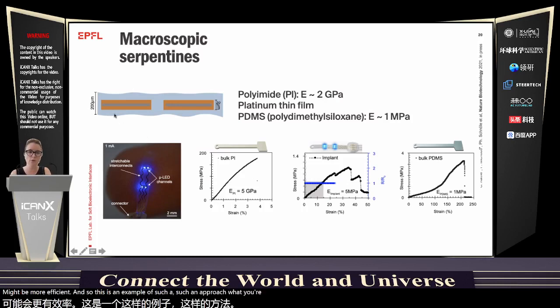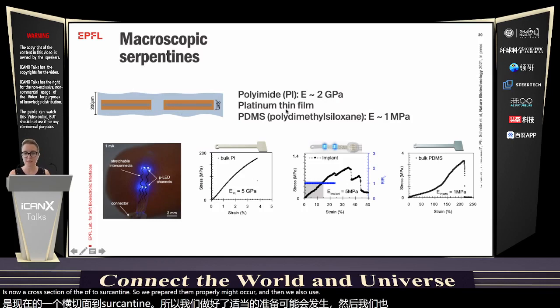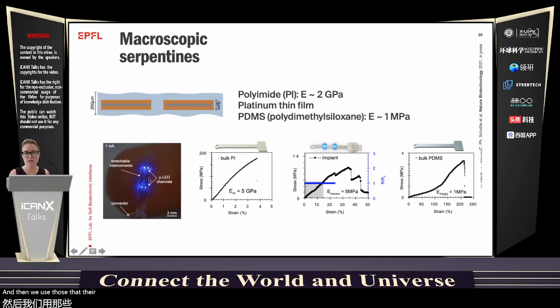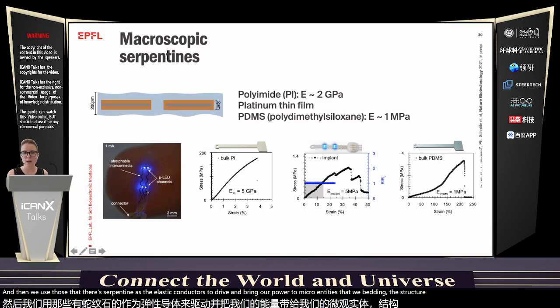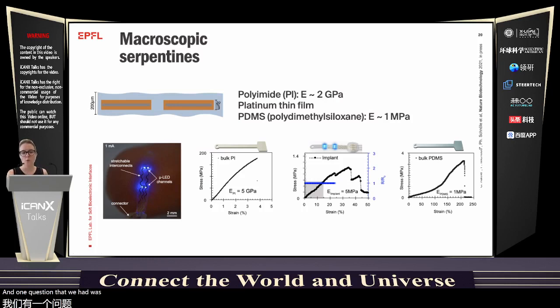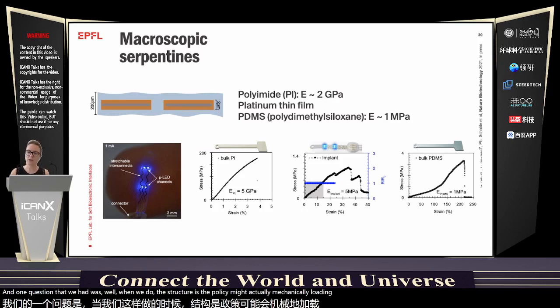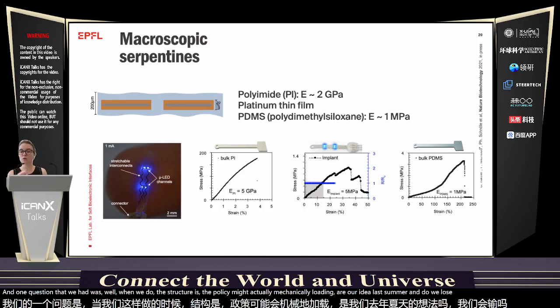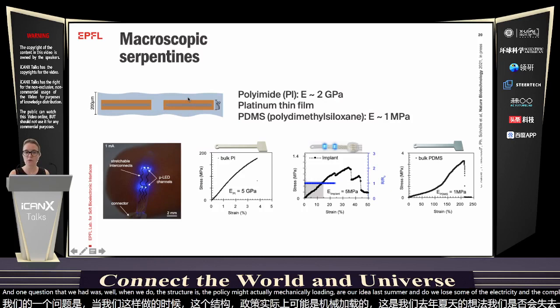What you're looking at here is now a cross-section of two serpentines. So we prepare them in polyimide, and then we also use platinum as the electrical conductor. And then we use those serpentines as the elastic conductors to drive and bring power to micro LEDs that we embed in the structure. And one question that we had was, when we do the structure, is the polyimide actually mechanically loading the elastomer, and do we lose some of the elasticity and the compliance by doing this hybrid structure that is composed of the polyimide with the elastomer?